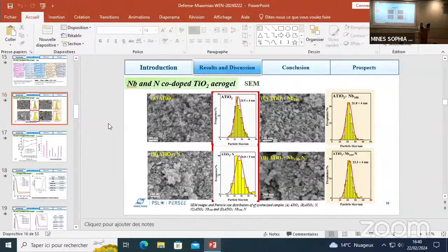Have you looked at the isotherm, because we don't give the picture of the total isotherm? You make it because you give some pore volume. So do you remember the type of the isotherm? Because we have some porous materials. Do you know the different types of isotherm for porous materials? Probably it's type 4, the one with mesopores.